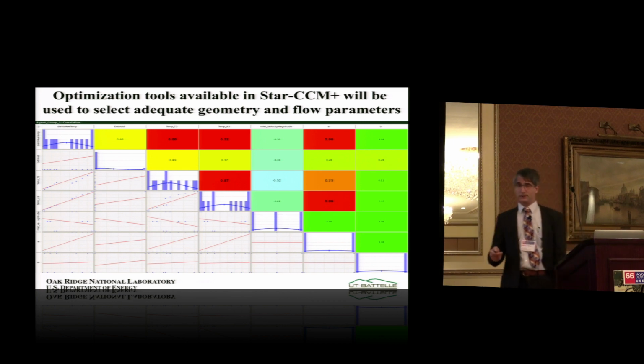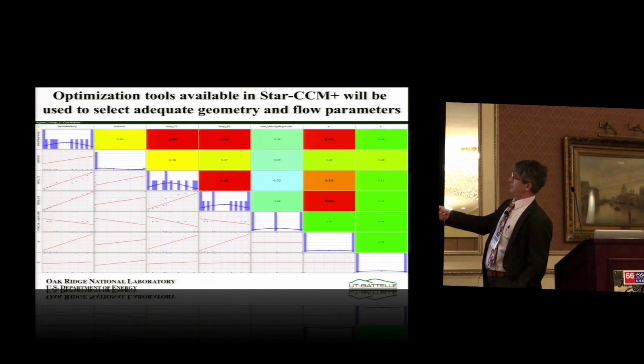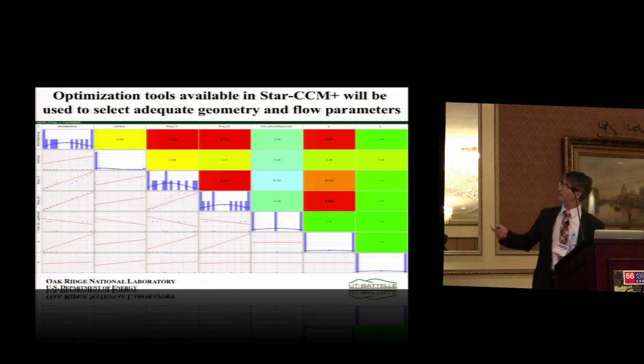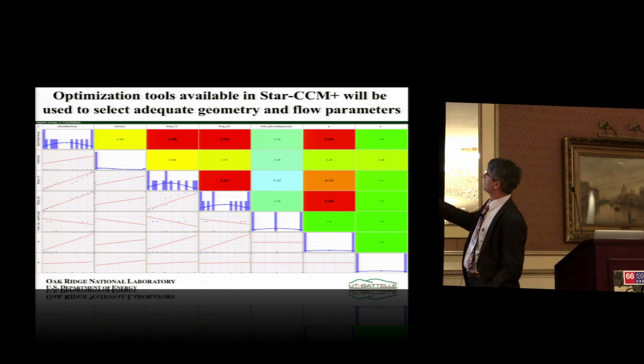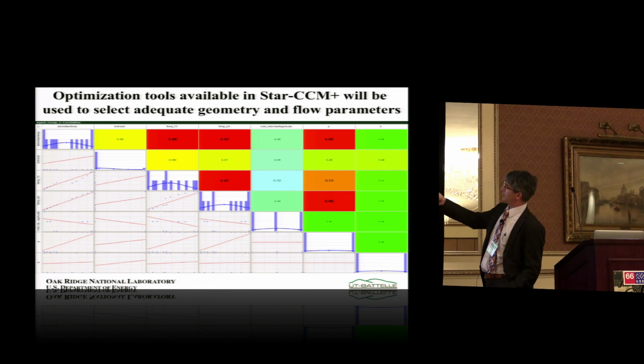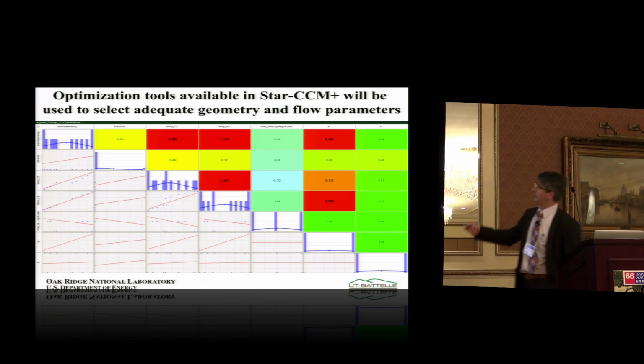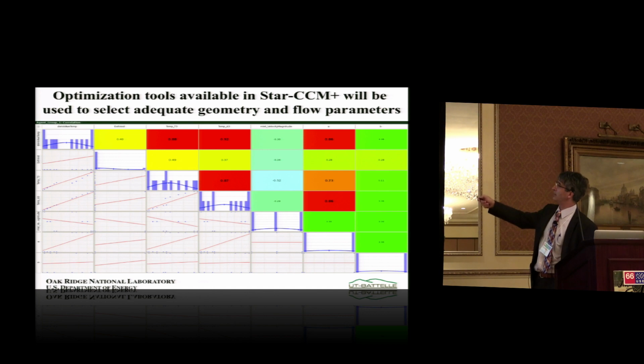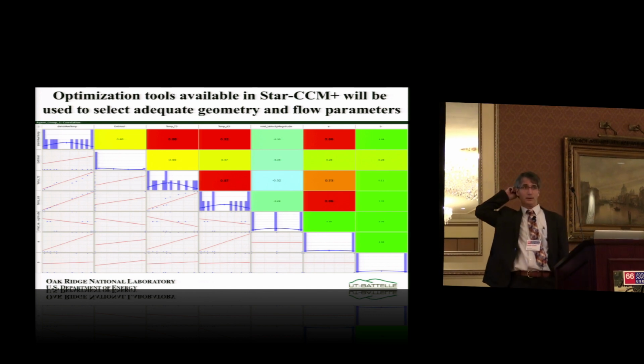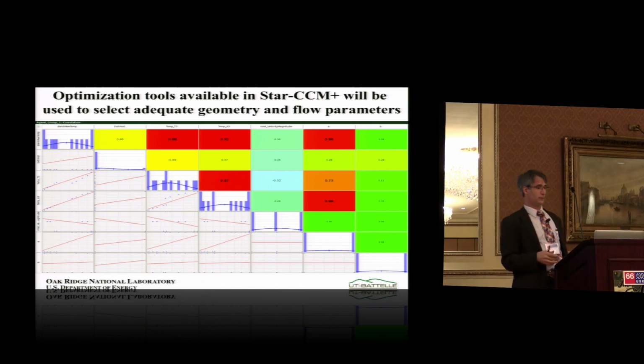What you see here is kind of a sensitivity analysis. What this tells you is that, for example, this is the effect of the coolant-to-die thickness. So the higher the number from 0 to 1, the more sensitive the variable that we're going to follow is going to be. So we identify that this is very critical. It turns out that the dimension of the cooling channel is not that important. Interesting.